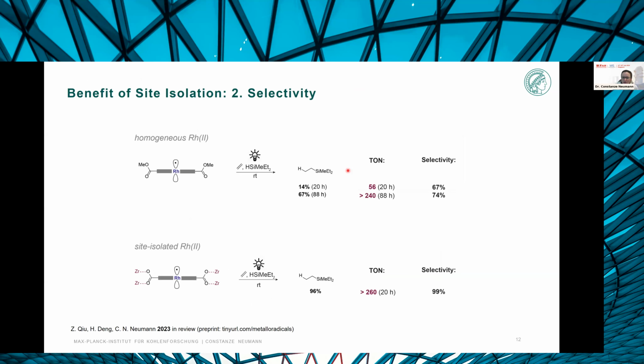But even for the light-mediated transformation, which can to some extent also happen for the molecular system, even if it proceeds at slower rates, we observe a significantly lower selectivity than we get with the MOF system, where we also get faster reaction rates.